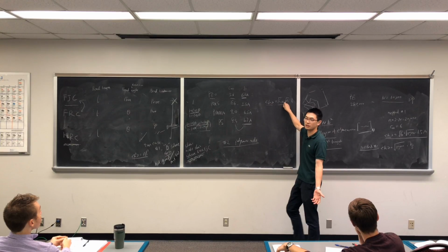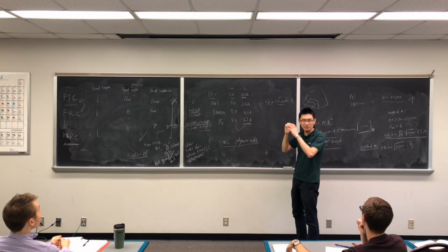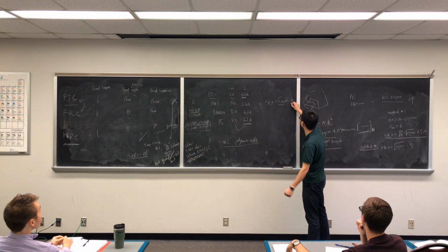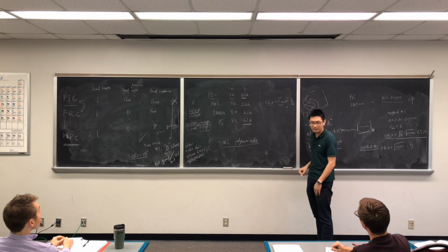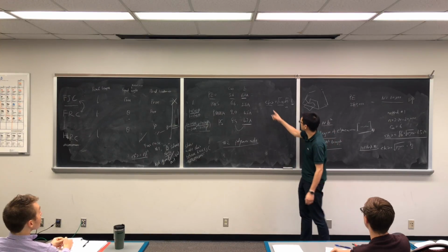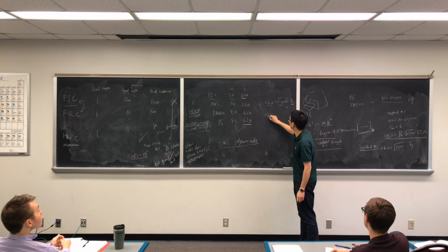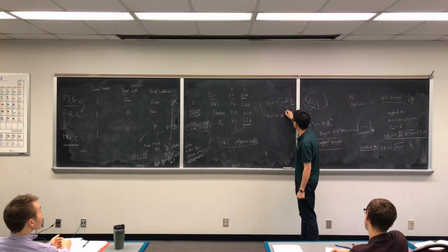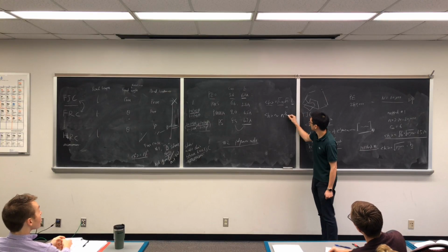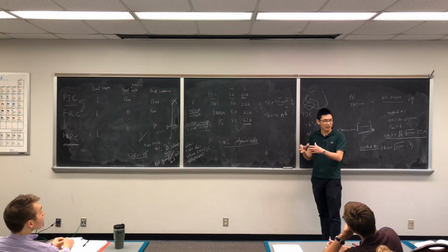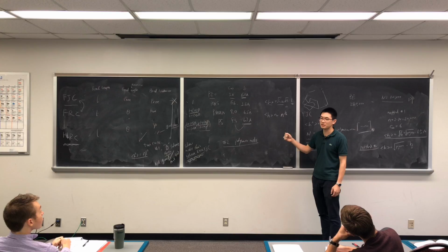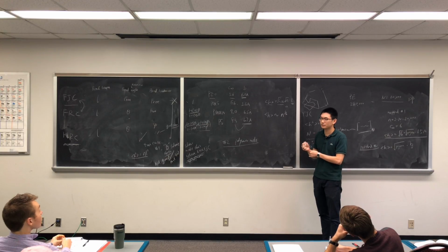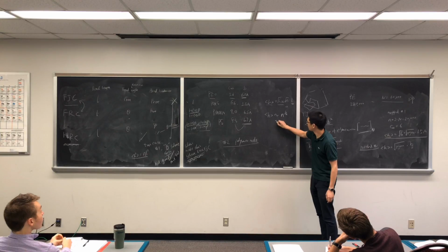So if you watch carefully, this is basically a constant. Well, we talked about it at the beginning of the class. The bond length, if you know, its value is fixed. So what only changes is n. And how do these relate to each other? We can basically write h is proportional to n to the power of half. So that means whenever n doubles, h only increases by a factor of root 2. This relationship is called proportional.